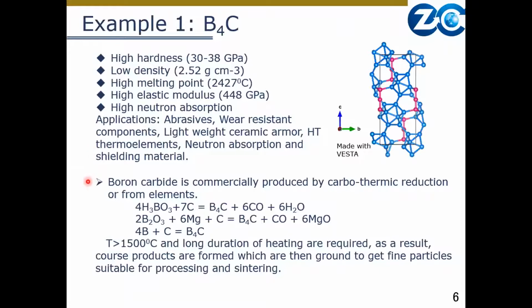Commercially, boron carbide is produced by two methods, carbothermic reduction or from elements. But all these methods require temperatures higher than 1500 degrees and long duration of heating. As a result, coarse products are formed. And to process them, we need to grind them to get fine particles. And then it takes a lot of time because boron carbide is very hard.